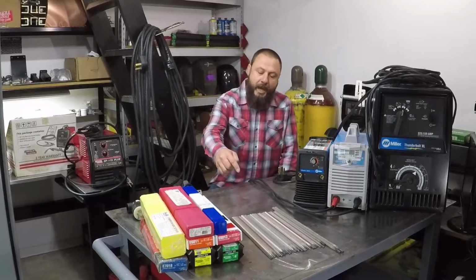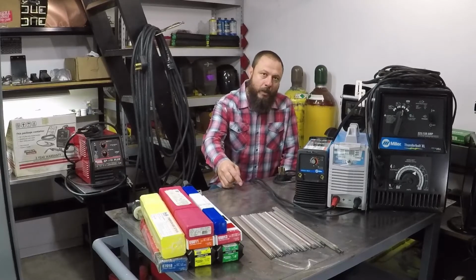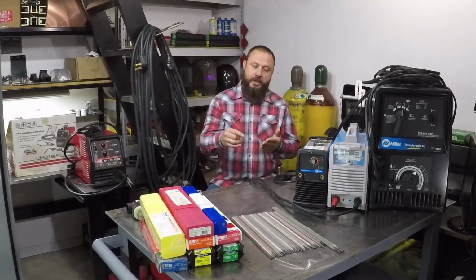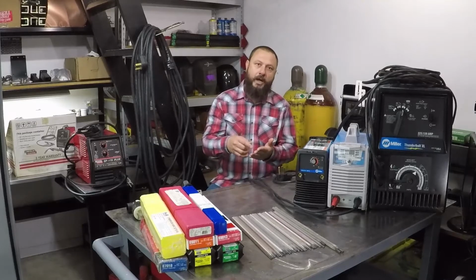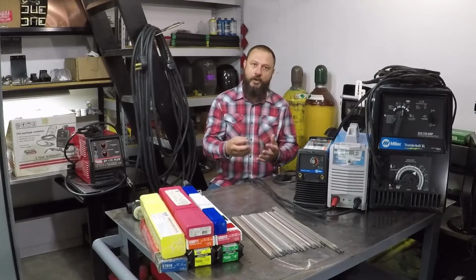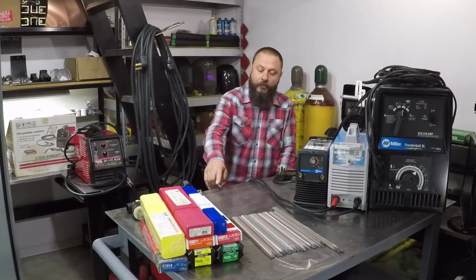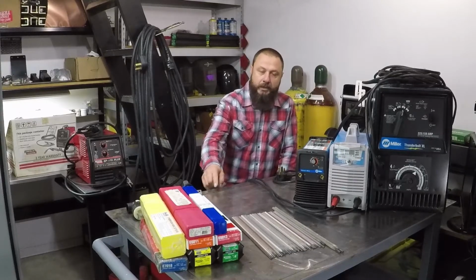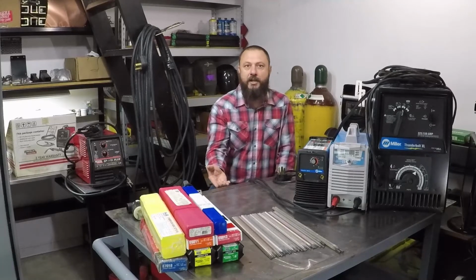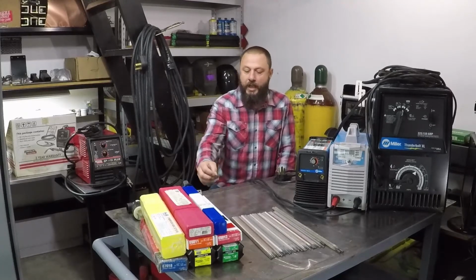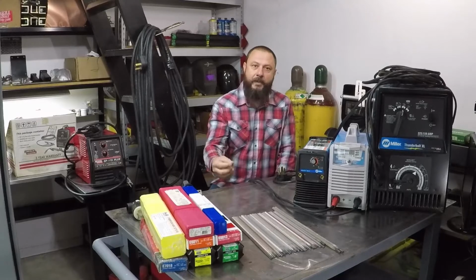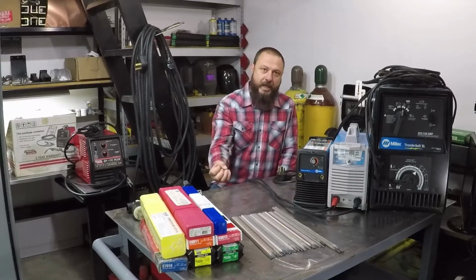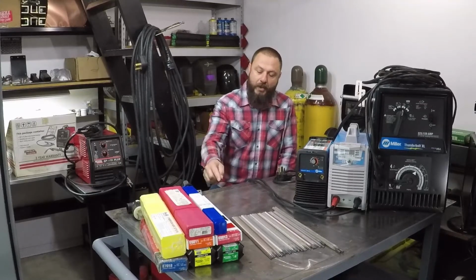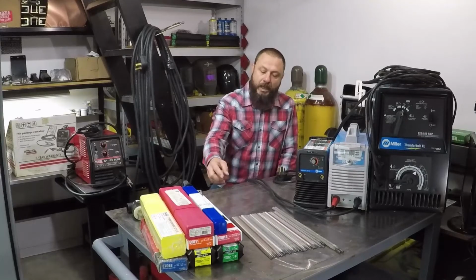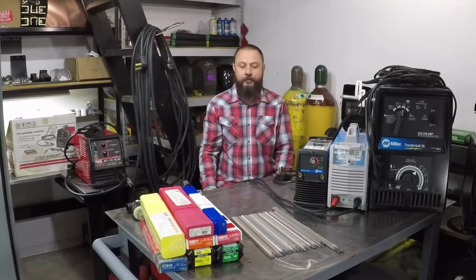Other times it happens if the arc length is too long. You're allowing oxygen and nitrogen to get into the arc, and this will mix with the melting metal and cause these holes. Or if you try to weld and there is water underneath the metal or inside the joint, the water starts to evaporate and the gases released from the water will mix with the metal and cause porosity.